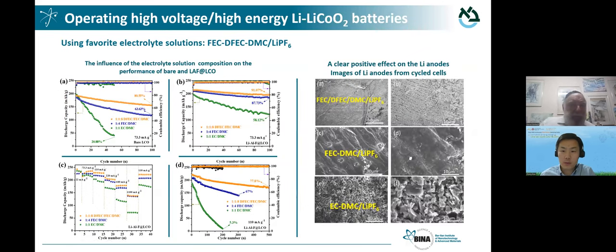The last example of modified cathode materials is lithium cobalt oxide. Lithium cobalt oxide, in fact, is very commonly used. All your laptops and cellular phones are operated by graphite LCO cells. And usually the operation is up to 4.2, 4.3 volt, which means that we extract a capacity of 150 milliampere hour per gram. But there is an option to increase the voltage up to 4.6, even more, and then reach a very high specific capacity above 200 milliampere hour per gram.